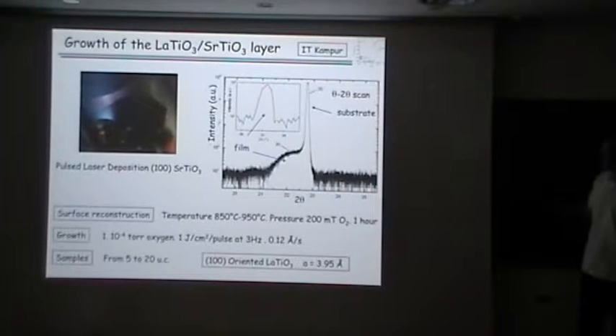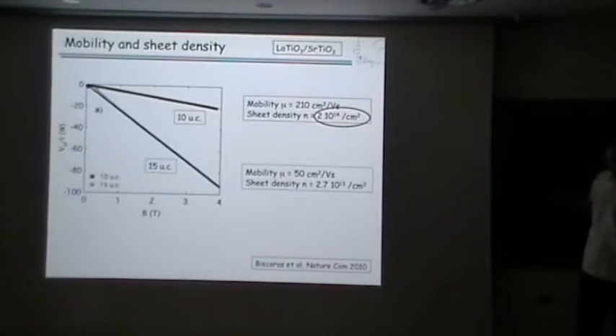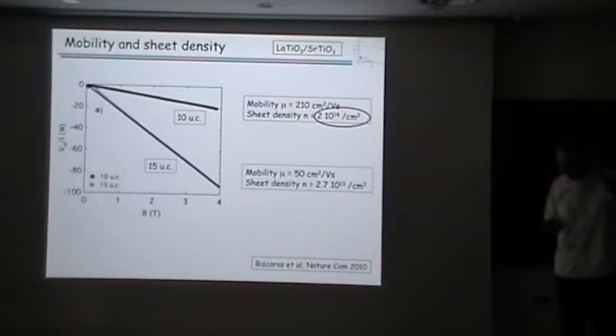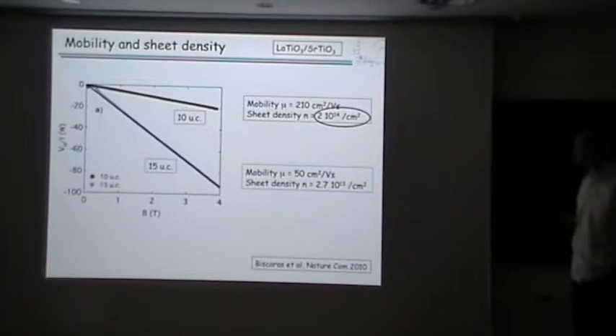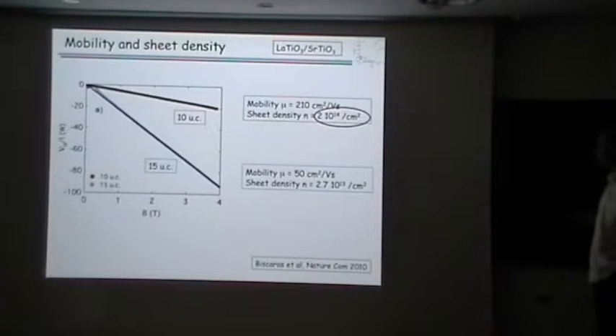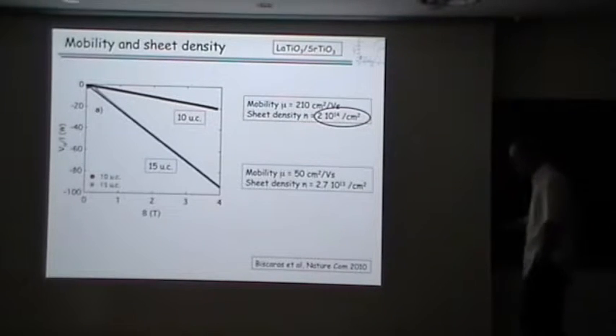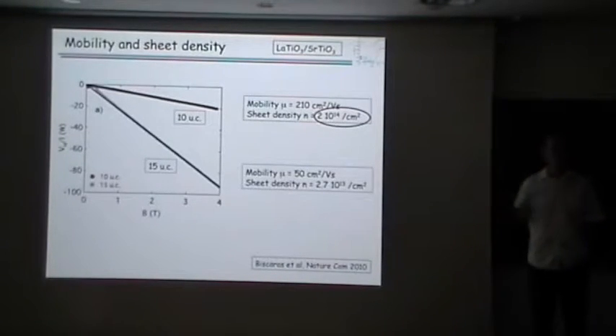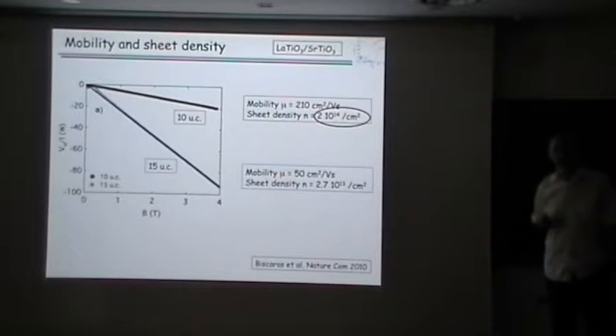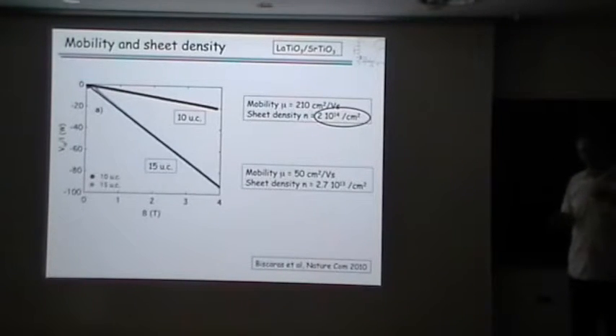Okay, I will skip the details of how the samples are grown in Kanpur in India by the group of Professor Budhani, and so we can have different samples with different thicknesses. This is the number of unit cells: 10, 15. Below 5 unit cells there is no conductivity at all. Above 20 or 25 the conductivity is very poor, but this is known because above this thickness the strain is relaxed and there are cracks and stuff like that. So the samples are not good anymore.